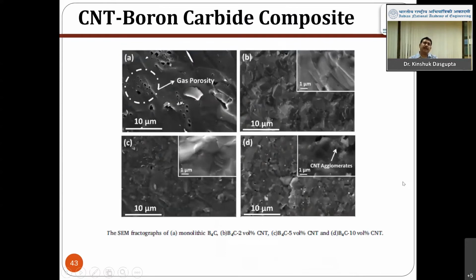Now I will come to how carbon nanotube improves the property of ceramics as a filler, because this has very good application in the impact kind of application. So here boron carbide is a ceramic. As we know, we are using boron carbide in atomic energy as control rod material, and boron carbide is also used in other applications like armor, and even for the cooling purpose. So here I am showing that if we add carbon nanotube during the hot pressing of boron carbide, which is generally produced by hot pressing, what happens first of all to the structure?